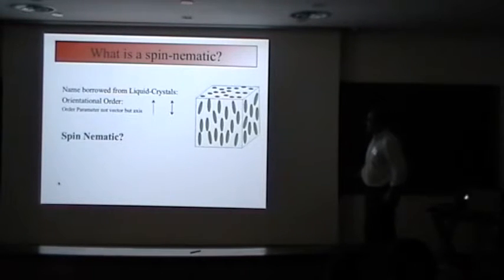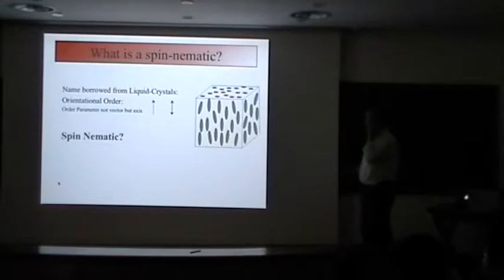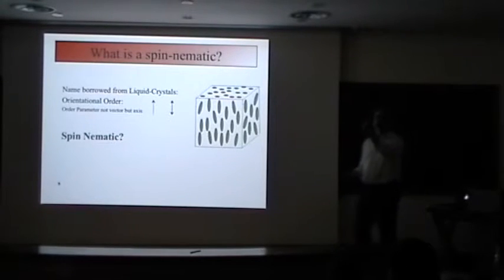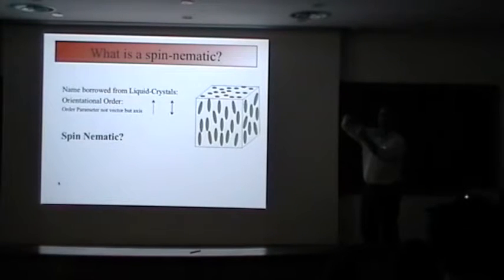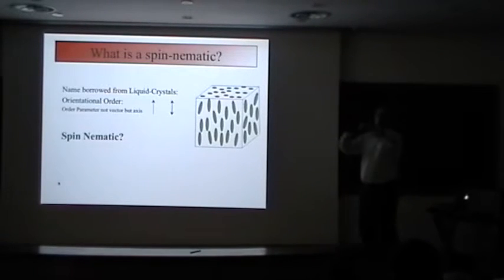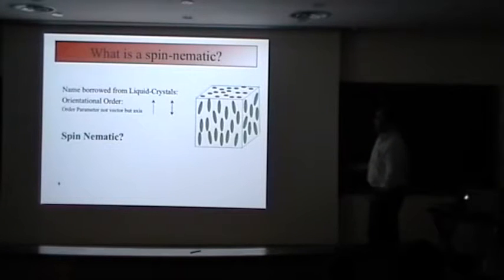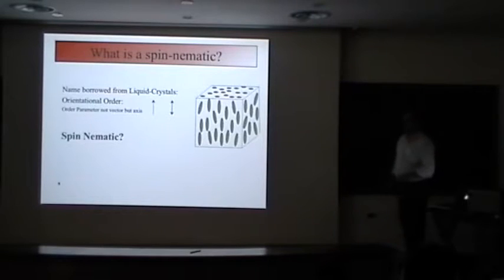This idea is taken over from liquid crystals, in which there's orientational order, so that the order parameter is not a vector pointing in a particular spin direction, but is an axis where, say, the sublattices of the spin on each neighboring site are always pointing parallel or anti-parallel, but allowed to rotate together with each other and give no net moment, yet have a well-defined order parameter. So there's an axis which is selected, but not a particular direction of a vector.